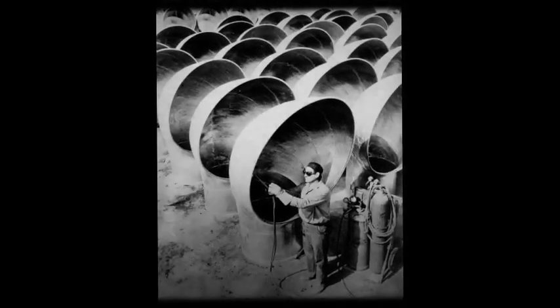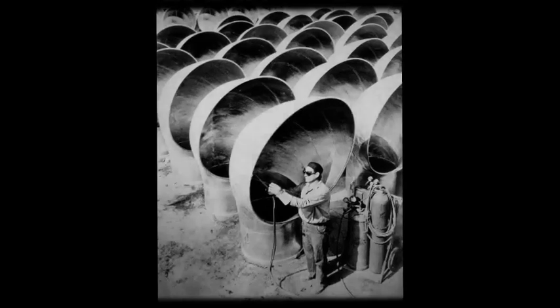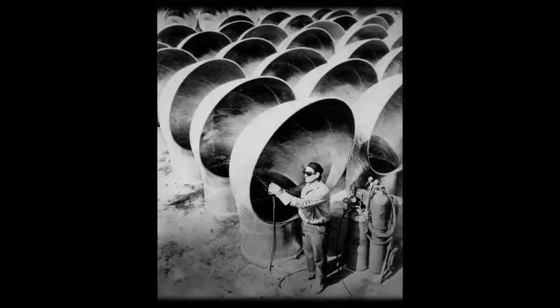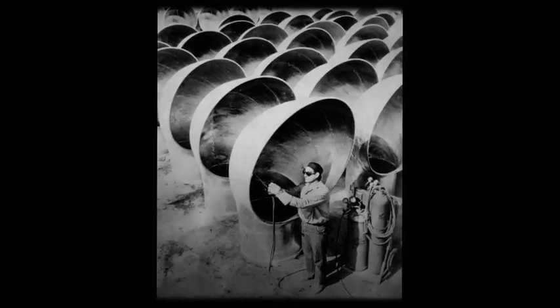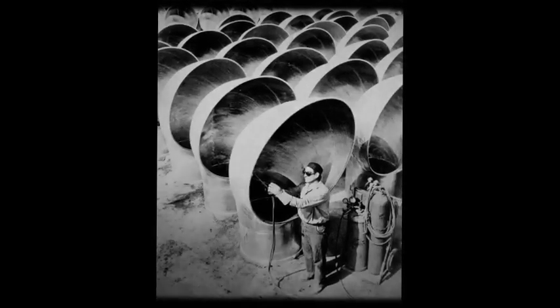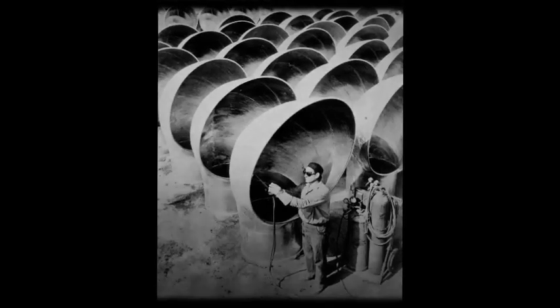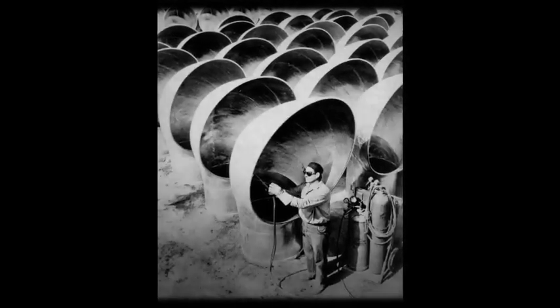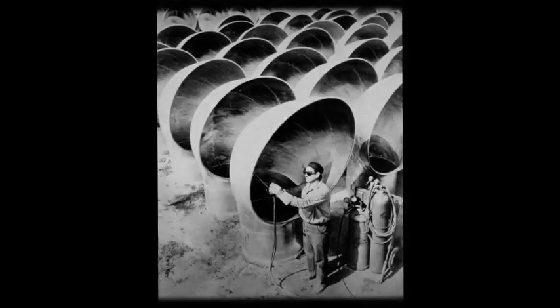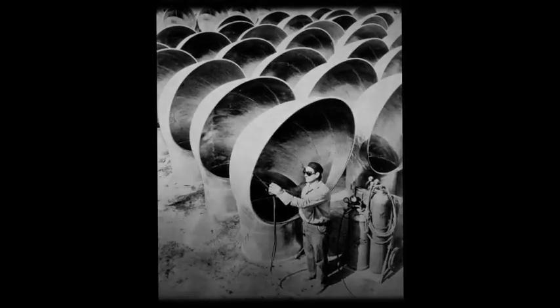The crack sped up fast, sometimes even faster than the sound moving through the metal, racing across the hull before any walls or beams could stop it. The SS Schenectady's break now made perfect sense. She was built in early winter, welded in a way that locked in stress. Her hull carried millions of pounds of tight tension. When the Portland air dropped to 28 degrees, the steel turned brittle.